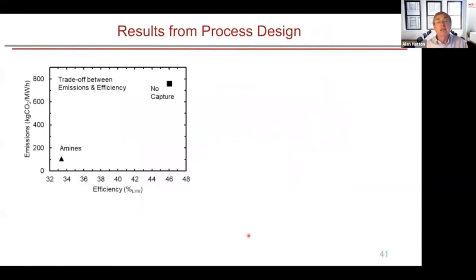We've done a fairly detailed Aspen design analysis of the systems. This is the rate efficiency of the power plant. This is the emissions in kilograms CO2 per megawatt hour. If we have no capture, the emissions are pretty high. Efficiency is about 46%. If we have capture, the net efficiency is going to be about 33%, and we get about 80–90% capture. And emissions are greatly reduced. If we use our molten salt systems, according to our analysis, we get this range over here. The various cases we looked at, where the emissions level are similar to what we have for the amines, but the efficiency of the overall plant would be significantly better.